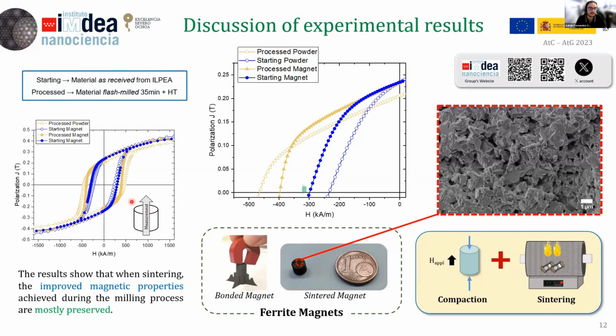So here you can see the full hysteresis loop, and here the second quadrant. We can see that we have an increase of almost 100 kiloamperes per meter between the magnet using the starting powder and the magnet using our post-processed powder by flash milling 35 minutes and a recrystallization process. So we managed to improve the magnetic properties, and we managed to mostly preserve them during the sintering process.